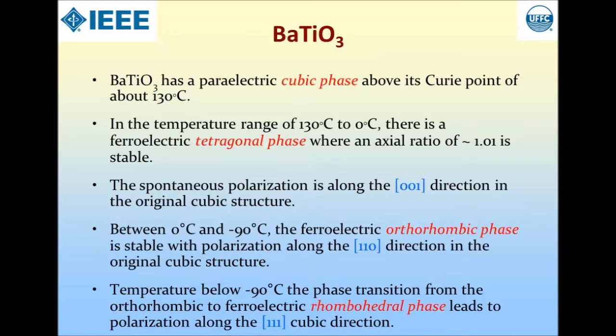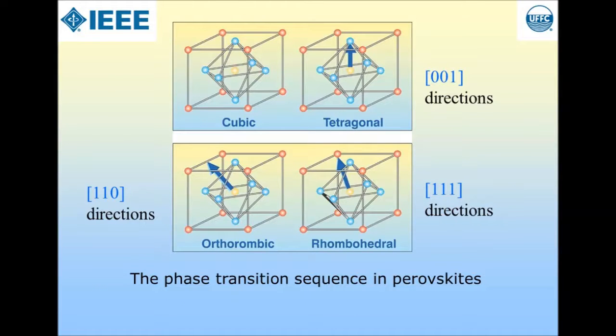In the temperature range of 130 degrees Celsius to 0 degrees Celsius, there is a ferroelectric tetragonal phase, where an axial ratio of 1.01 is stable. The spontaneous polarization is along the 001 direction in the original cubic structure. Between 0 degrees and negative 90 degrees Celsius, the ferroelectric orthorhombic phase is stable, with polarization along the [110] direction in the original cubic structure. At temperatures below negative 90 degrees C, the phase transition from orthorhombic to ferroelectric rhombohedral phase leads to polarization along the 111 cubic direction. The following is the phase transition sequence for barium titanate, going from cubic to tetragonal to orthorhombic and rhombohedral.